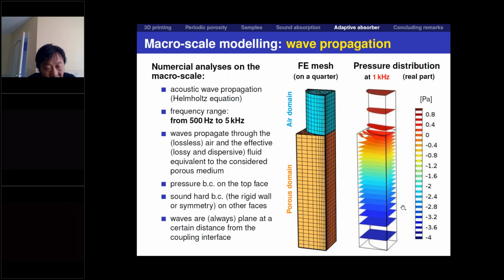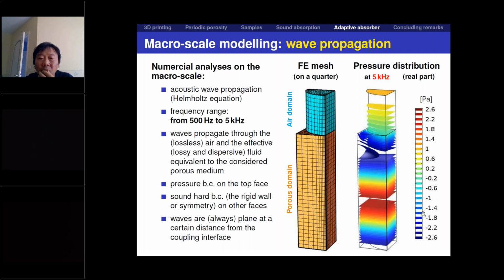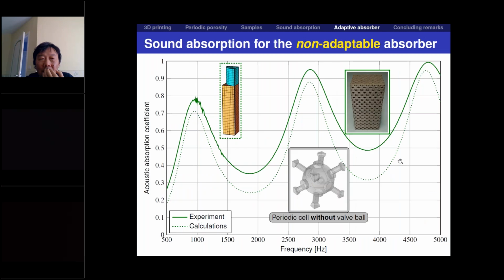Even on the macro scale level, we need to calculate the problem using the finite element method, because we have this cuboidal porous domain linked with a cylindrical air domain. Here we do our computations on the quarter of this problem. And you see that close to the interface between the air domain and the porous domain, we have non-planar wave propagation. So we need a finite element method to calculate this problem.